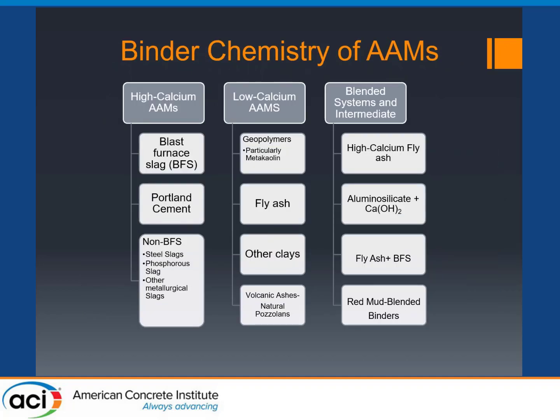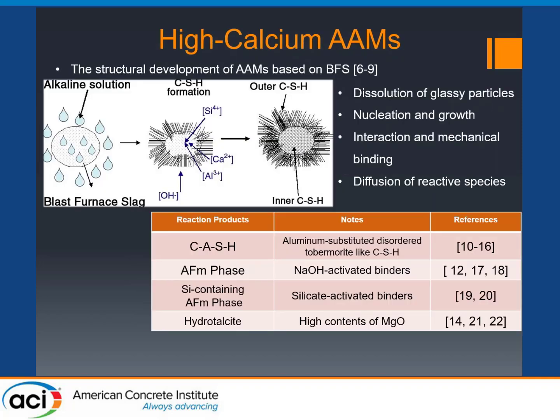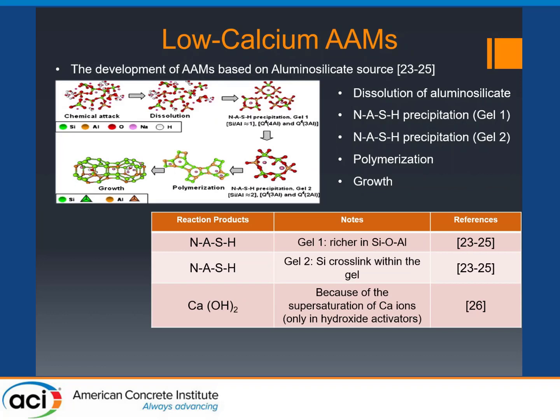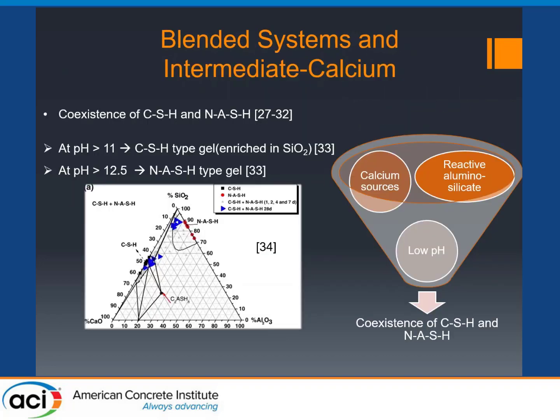And based on the binder chemistry, we could have high calcium AAM, low calcium, and blended systems. Okay. So for example, under high calcium AAM, the reaction products include C-A-S-H, which is a poorly ordered tobermorite-like CSH, AFm phase, among others. For low calcium AAM, we have that classic famous geopolymer, N-A-S-H. And also we could have calcium hydroxide. Okay. And for the blended system, we could have a mixture of CSH, C-A-S-H, N-A-S-H, and depending on the pH level, we could have different types of hydration products.